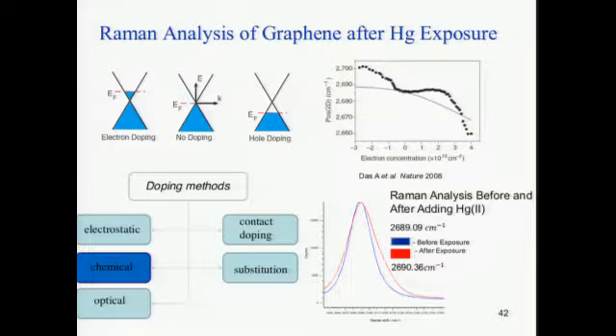or hole doping. As you go higher in the wave number, particularly at this 2D peak in graphene, that's indicative of hole doping. So I'm reluctant to say, but hopefully we possibly could have changed the Fermi level, the energy of the Fermi level, by hole doping. And so right now we're really looking at chemical doping techniques.